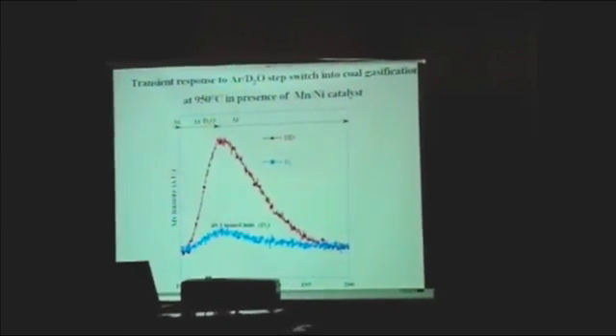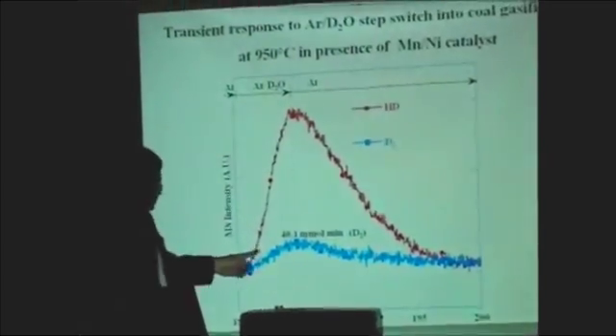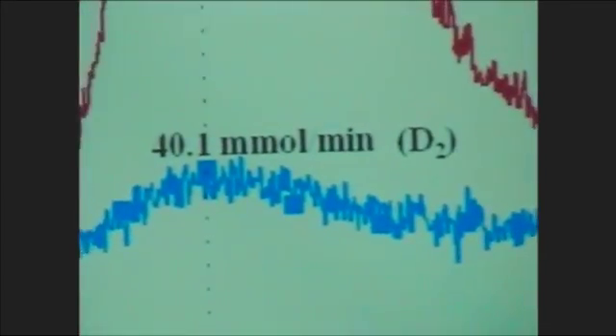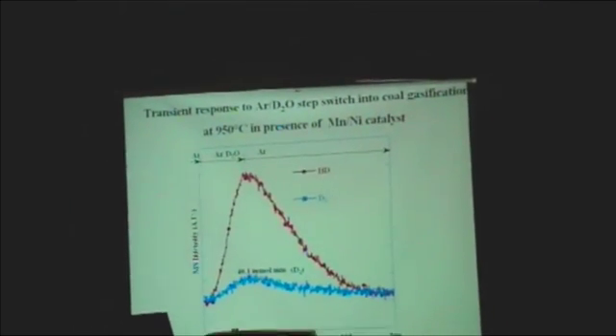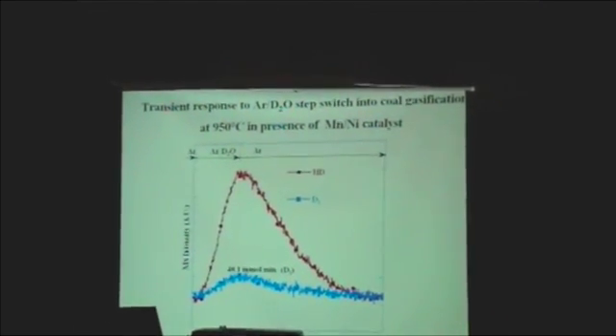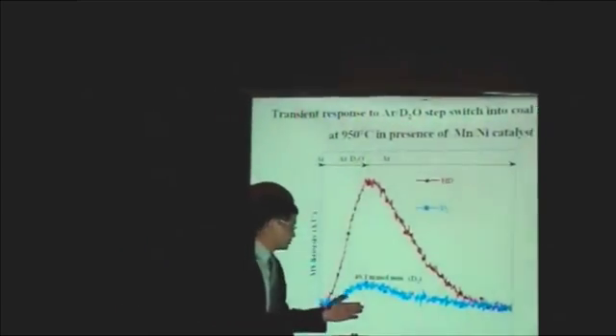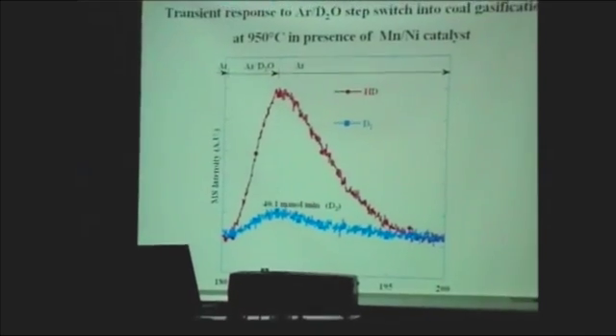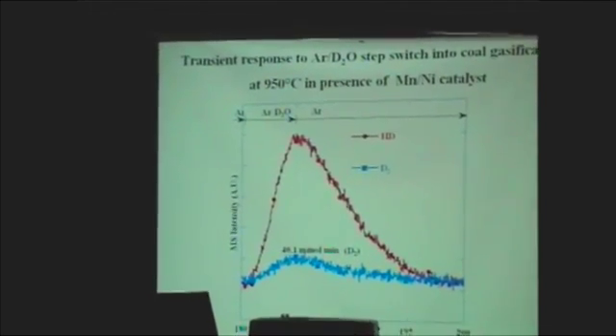This catalyst indeed is a very good steam reforming catalyst. What we found here is that we passed D2O through this coke, and we generated a large amount of HD. The H primarily comes from the coal, which is still on the coal. And we also see a large amount of formation of D2 out of this reforming reaction. This data was taken about 2 or 3 years ago. And recently we have rerun it. We were able to reproduce the data. We were also able to produce CO and CO2. So for each mole of D2 produced, we also produced about 1 mole of CO; the amount of CO and CO2 added up together is about 1 mole.